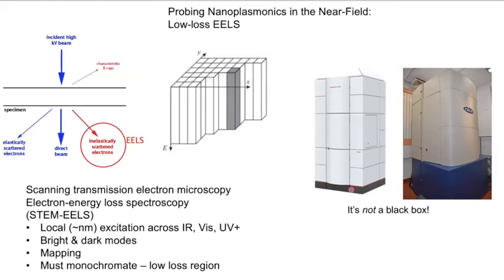Okay, so what we're going to do here to look at the near field is take an electron beam and actually scan it everywhere around our particle. At the end of the day, what we want is a map of the modes of the particle. At what energy is there high electric field? Where is this high electric field? So we're going to create a spectrum image like I'm showing here, where we have the two spatial dimensions and then an energy dimension. And we're somehow going to extract maps out of that.